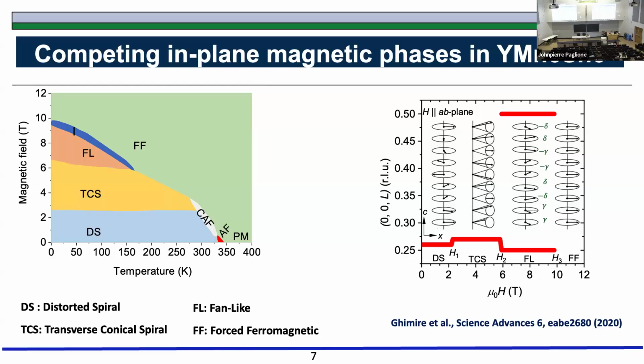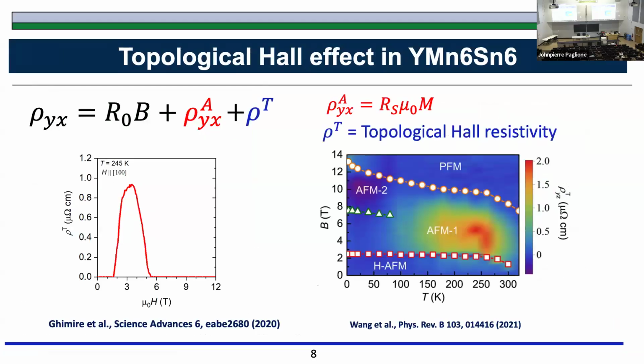And then it flops back into the plane and forms this phase and goes on. So there are many different magnetic structures that we can determine. Why we are even interested in determining this magnetic structure is that during this process, what we found is that in one of the regions, on one of these phases, we saw very unusual behavior. That means when we were measuring Hall effect, it had some additional signal that was not supposed to be there, which, again, I will not go into the details of all these things.